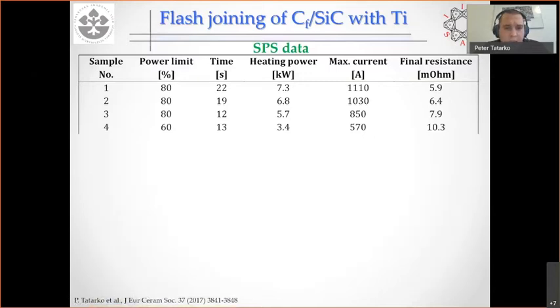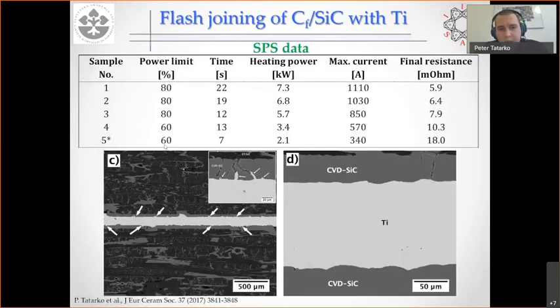So what we did then is we kept the same power limit, but we just reduced the time. You see, we used only 7 seconds in this case. And you can see now, no melting of titanium, no decomposition of CVD silicon carbide. So basically, we got a really nice joint. We don't see any significant reaction between the joining filler and the CVD silicon carbide coating.